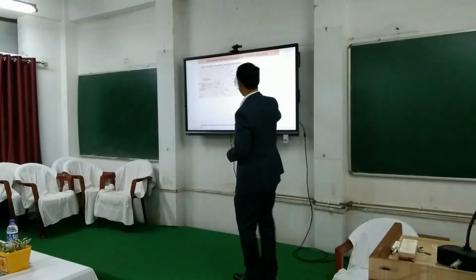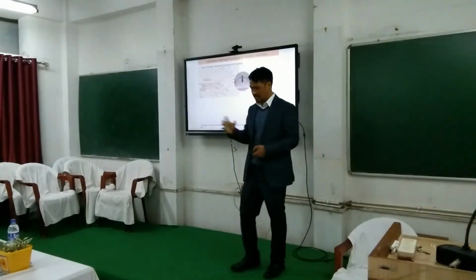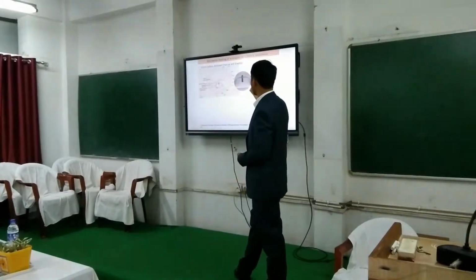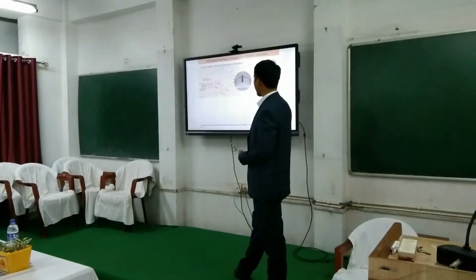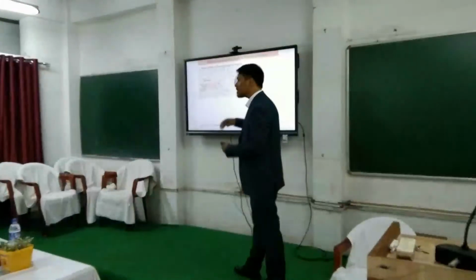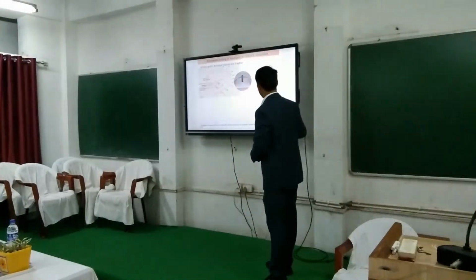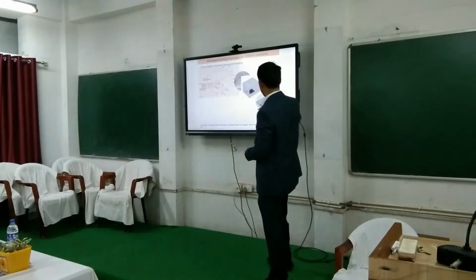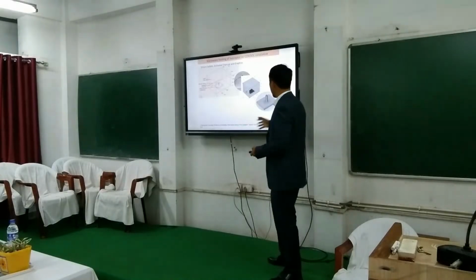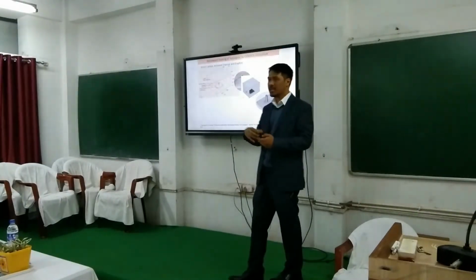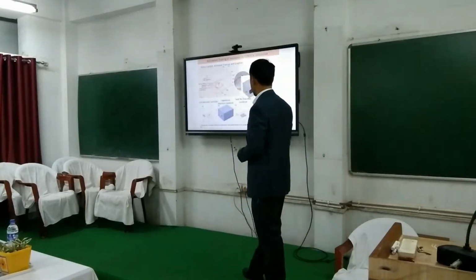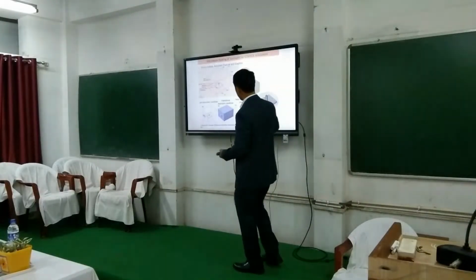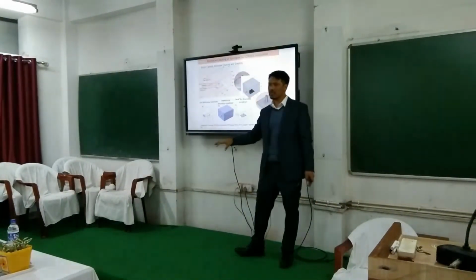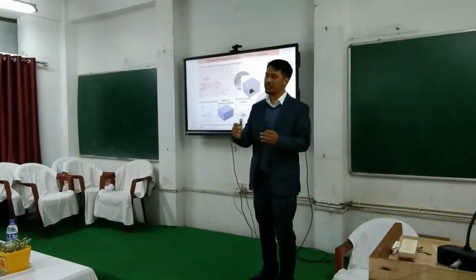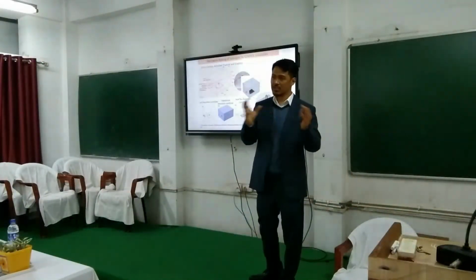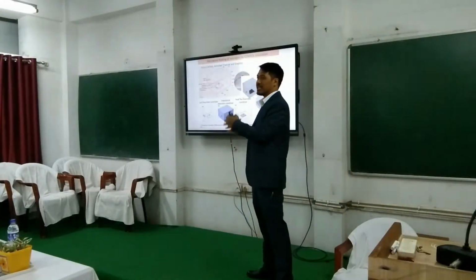We took cylindrical susceptors of different materials. This is silicon carbide. Then we placed it in the microwave oven and heated it up, and then we made this model in COMSOL, and also tried to simulate the heating in COMSOL Multiphysics. In Multiphysics, we applied multiple boundary conditions, which will help us to simulate the actual welding process, or in this case, the actual heating process.